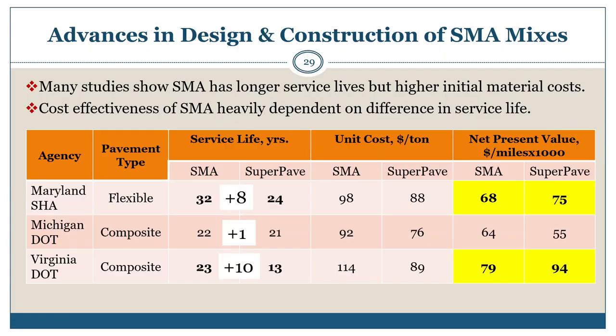The service life difference is shown in the first 2 columns for Maryland, Michigan, and Virginia. Michigan only reported a 1-year extended service life above dense graded mixes for the SMA mixtures. However, Maryland reported 8 additional years of service life, and Virginia has reported 10 additional years of service life for SMA mixtures.